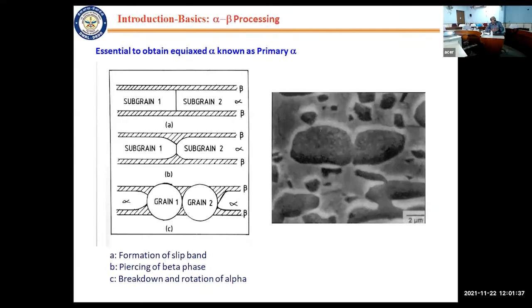The other important thing which you all should know is the globularization of alpha in titanium alloys. As I told you, this is beta and this is alpha. They occur as needles, or depending on the cooling rate, they will be thicker or thinner. Now, this is a very, very important treatment. Suppose you want to convert alpha from the lamellar structure to a globular structure, it cannot be done just by heat treatment as in steel. Normally, it occurs as laths. You have alpha and beta, very thin beta around. So what you have to do is a deformation in the alpha plus beta temperature regime, when formation of slip bands occurs.